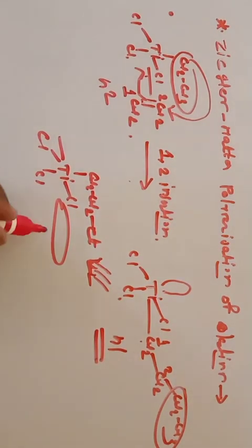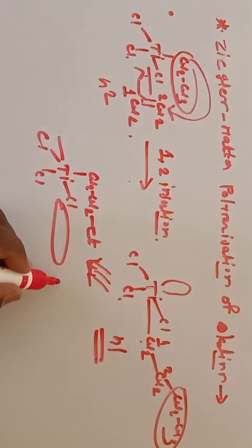Again there is a vacant site, and the coordinated alkene, the olefin, interacts with this vacant coordination site. So let's discuss the next step, the polymerization. In the first step, the chloride is replaced by an ethyl group, then the olefin coordinates to the TiCl3 Et complex, and then there is a 1,2 insertion.